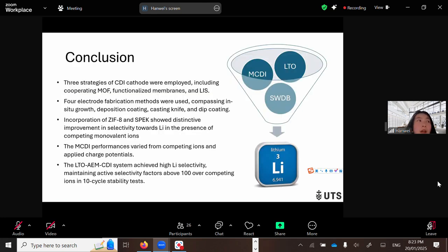Here is the conclusion. In my PhD research, I used 3 strategies of CDI cathode, including incorporating MOF, the functionalized membrane, and the lithium-ion sieves for CDI to extract lithium from diluted lithium brines. And 4 electrode fabrication methods were used, which are in situ growth, deposition coating, casting knife, and dip coating. And the incorporation of the MOF and the SPEK membrane shows distinctive improvement in selectivity towards lithium in the presence of the competing ions.